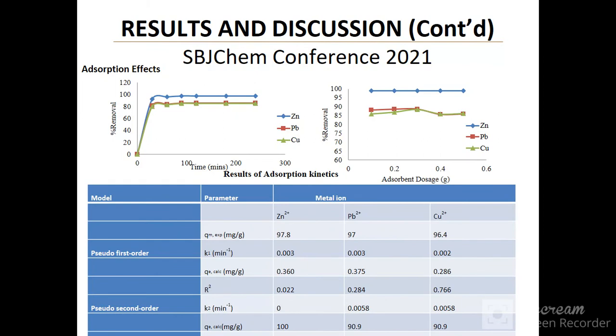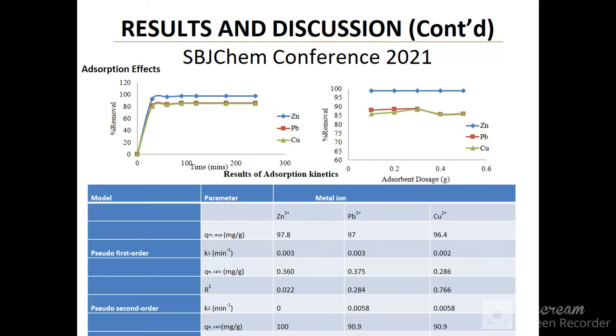Results of the adsorption show that time affected the rate of adsorption, with equilibrium reached around 90 minutes. Adsorbent dosage also affected the rate of adsorption, with a dosage of 0.4 g found to be most suitable. The pseudo-second-order kinetic model better represented the adsorption kinetics.